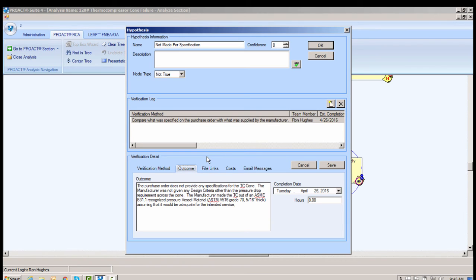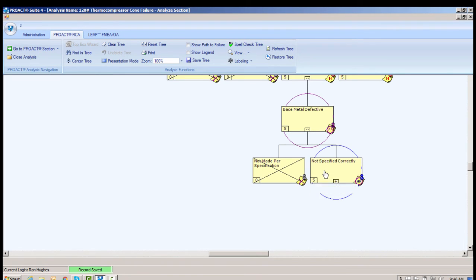Now, the owner of the plant is depending upon the manufacturer of the TC cone to spec the correct material themselves. So the manufacturer made the cone out of, like I said, ASTM A516 grade 70 material, 5/16 of an inch thick. Now this is fine for most applications, but it's not fine for this particular application due to the pressures and temperatures that we were seeing. So what he assumed was, okay, this worked at other places, it will work at this plant also. And that's a bad assumption. So it's not specified correctly.